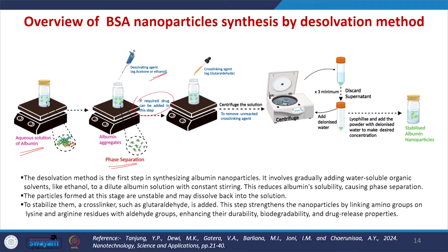As I told you earlier, most of the anti-cancer drugs are hydrophobic in nature. We can dissolve the anti-cancer drug in ethanol or acetone, and we can also add it dropwise. Then the drug will be encapsulated into the nanoparticle. The albumin aggregates or nanoparticles formed at this stage are unstable. They may dissolve back into solution. To avoid that, we have to add the cross-linking agent, that is glutaraldehyde.